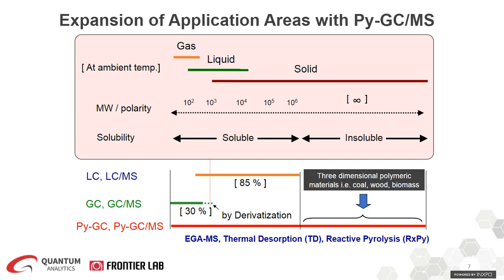So there are also some solids that are insoluble and cannot be analyzed by LC, LCMS, GC, or GCMS. But these insoluble compounds can be analyzed by Pyrolysis-GC, and that's really where the PyGC or PyGCMS comes into place and expands the capabilities of your GCMS. So using this technique, there is no need for any solvent extraction or sample preparation prior to your analysis. You could inject solid sample as is without any solvent. So as you could see now, the entire range of organic compounds from gases to solids can be analyzed using this technique. And that's really how the multi-mode pyrolyzer can expand your GCMS capabilities.